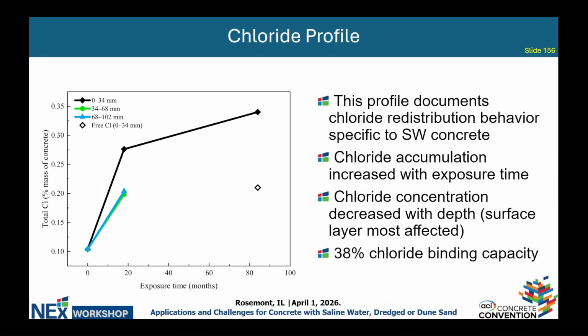So here is the chloride profile. The most important thing that I would like to highlight is the point after 7 years for the total chloride content as well as the free chloride content. If we compare between them, we can compute the chloride binding capacity, which is 38%, which means that more than one third of the chloride content inside this system is not available at the reaction site. It should be noted that we have the inner depths still in process for this test, and this is the initial theoretical value with the introduced chloride content in the system, this is after 18 months, and this is the 7-year value.